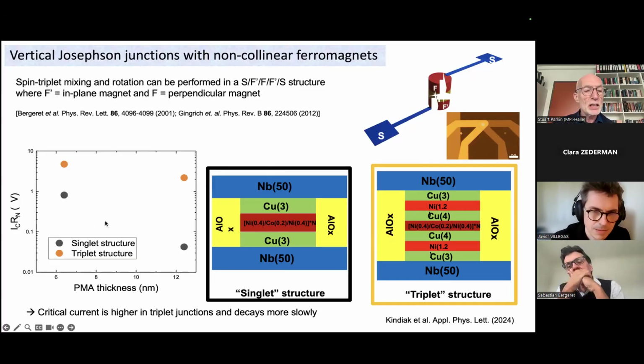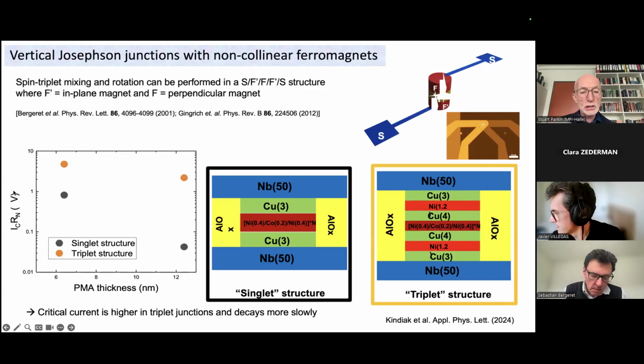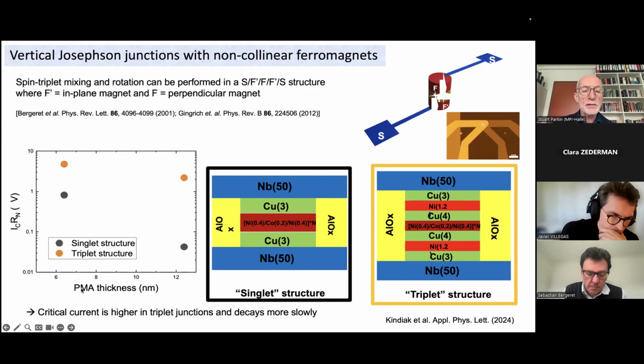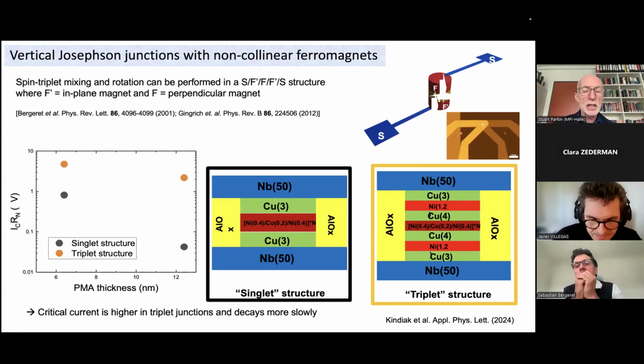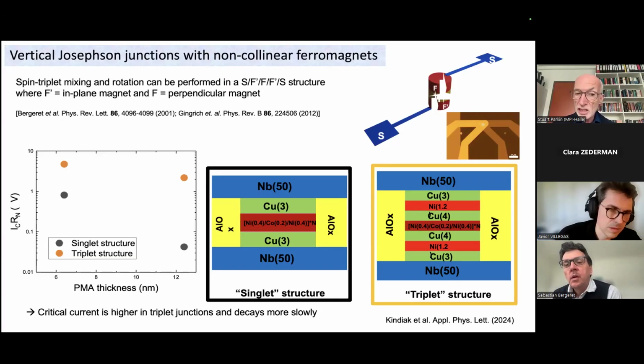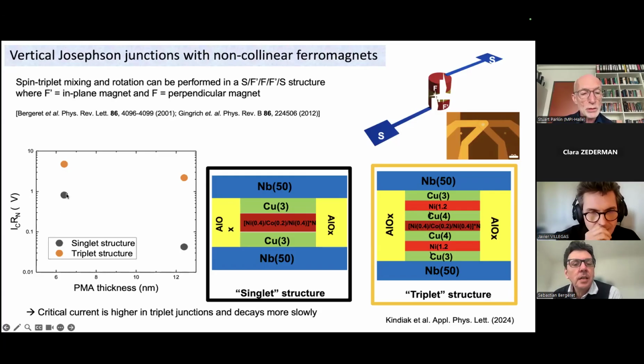On the left-hand side, you can see the black dots show the critical current as a function of the thickness of the PMA, the perpendicularly magnetized nickel-cobalt-nickel multilayer. Because the layers are so thin, the magnetization is perpendicular to those interfaces, just as in the racetrack I mentioned earlier. You can measure a critical current density for a certain thickness of that multilayer. As you increase the thickness, going from just beyond 6 to just beyond 12 nanometers, the black critical current density decreases by more than an order of magnitude. For this, I'm going to call it a singlet structure.